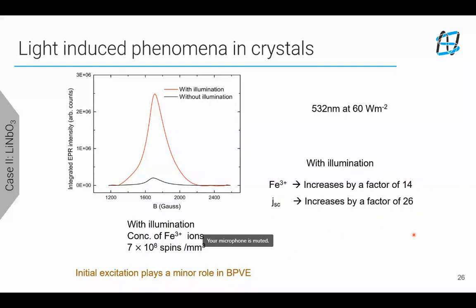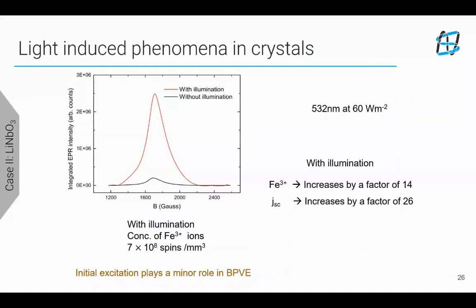So what is it? It must be this kind of polaronic motion, and it doesn't entirely depend upon the initial excitation. Meaning the optical light-induced phenomena that you're seeing in this crystal doesn't directly depend upon the initial excitation from the Fe to the neighboring ion, but on what happens to the electron once it went to the niobium site. So we determined that initial excitation plays a minor role in the photovoltaic effect, and that the polaron, the ballistic transport of the electron after initial excitation, is what really determines the light-induced phenomena in these crystals.